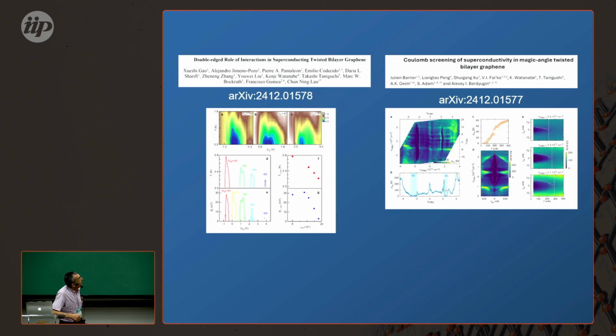And these are two experimental papers. We have participated in this one, which is Jeanie Lau and co-worker. This is a collaboration between Singapore and Manchester. What the experimentalists did for us was to tune the repulsive interactions by changing the environment, and in agreement with expectation, the superconductivity disappears as you increase the screening. That's particularly clear in the case of Jeanie Lau, because they were using strontium titanate, where you can change a lot the dielectric constant of the environment.